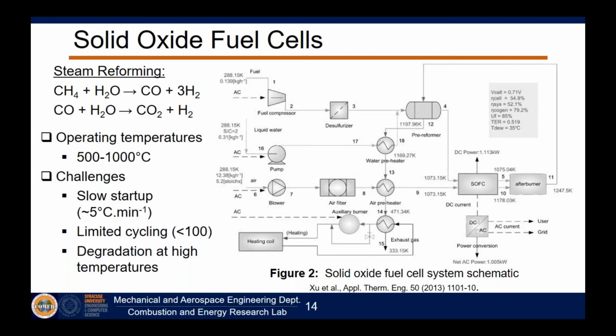Also, right now, the DOE and a number of organizations are really trying to push the limit of these solid oxide fuel cell systems to cycle, to basically turn on, turn off, turn on and off again. Very challenging, actually, because they're sealed so well that if we turn them on rapidly, and if we do it many, many times, those seals start to break. And so some of the challenges here, they're really trying to push 100 cycles. That's the goal. And of course, at high temperatures, these materials start to degrade, and we have a lot of compatibility issues with different materials going from ambient temperature all the way up to 1,000 degrees Celsius. So this is kind of big picture solid oxide fuel cells to give you a brief introduction.